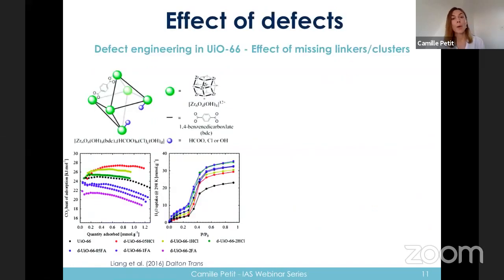I wanted to also give an example of the effect of defects that happens a lot, for instance, in MOFs, and I take here the case of UiO-66, which is a zirconium-based MOF. We have here the structure of UiO-66, and we have here a missing linker. And you can see that because of that, it will change depending on what the missing linker is replaced by, and you have different examples here. We will have different heat of adsorption for CO2. So the black line here corresponds to the defect-free MOF, and then the others correspond to the defective MOFs. Depending on the group or chemical you have attached here, you will have different heat of adsorption. And that will also show in your water isotherms here.